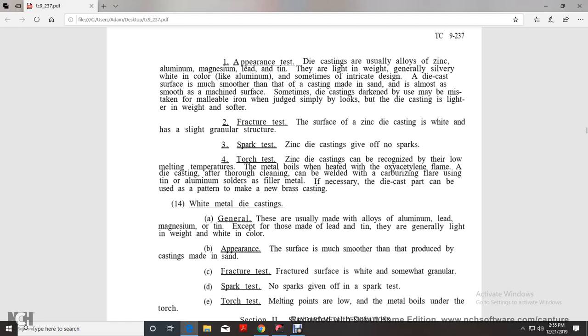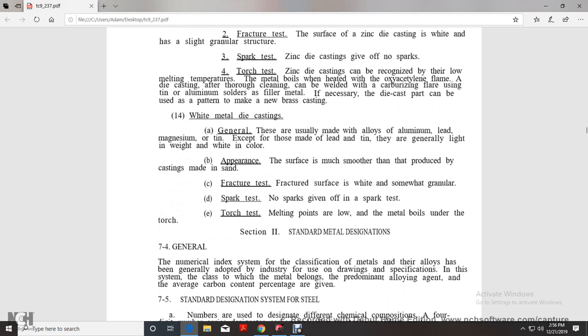The die casting is lighter in weight and softer. Fracture test: the fractured surface of the zinc die casting is white with a slightly granular structure. Spark test: zinc die casting gives off no sparks. Torch test: zinc die castings are recognized by their low melting temperature. They melt and boil under the oxyacetylene flame, and after cleaning, the die casting can be welded with a carburizing flame using a tin and aluminum solder as filler metal. If necessary, the die cast parts can be used as a pattern to make a new brass casting.